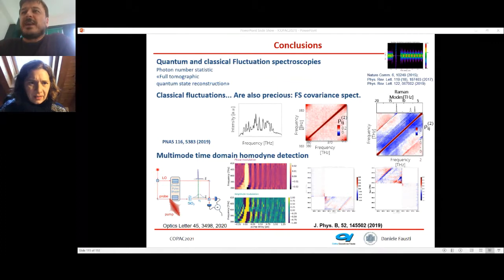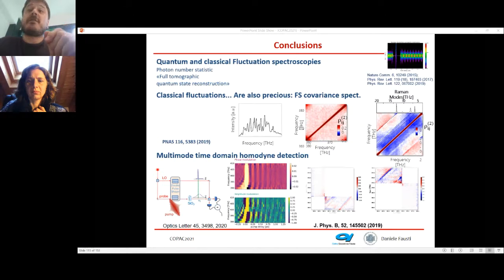The picture here? No, actually, this is the part I didn't detail. This is basically a coherent phonon measurement, but where I measure not only the intensity of my field, but the amplitude of the field and the phase of the field, through this heterodyne description which I haven't detailed here. The interesting bit is that if you measure also the phase, you see that while in the amplitude response you do have an anti-phase response between the frequencies on the blue side of the pulse and on the red side of the pulse, like you expect in impulsive stimulated Raman scattering, the phase response instead is the same for all the frequency components.